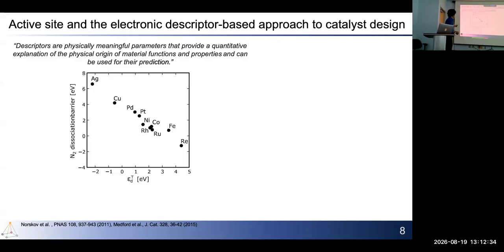Here's one example looking at the same reaction again, nitrogen dissociation. Instead of creating surfaces like in the previous example, this particular study computed the position of the D-band center of different metals. Transition metals usually have a half-filled S-band, and the D-band filling varies depending on where you are in the periodic table.